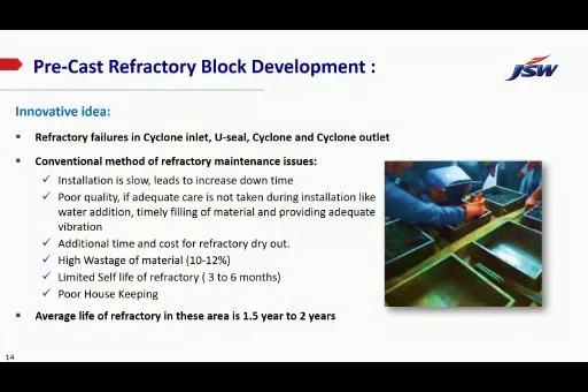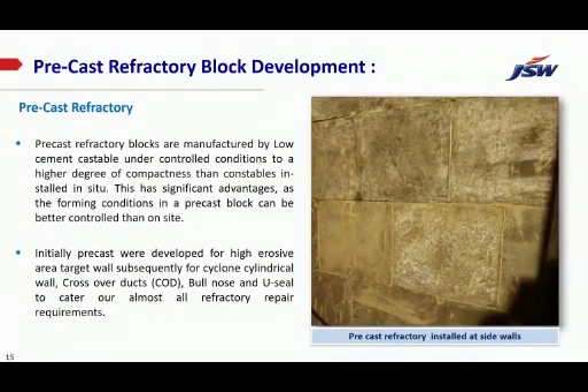So there are some issues in the maintenance of conventional refractory. The installation is so slow, so it increases the MTTR, and it is completely man-oriented work. So adequate care cannot be taken at every installation time, so quality is also poor. It takes additional time and cost for the refractory dry-out. And it is a manual installation, that's why the wastage of material is also high, and housekeeping is also very poor. After that, the average life of conventionally cast refractory is just about 1.5 years to 2 years. So to overcome all the problems, the precast refractory blocks concept has come into the picture.